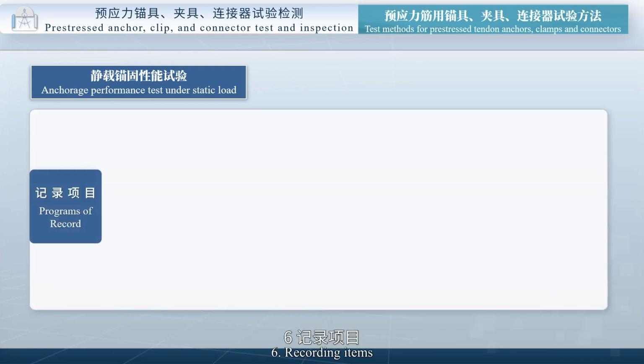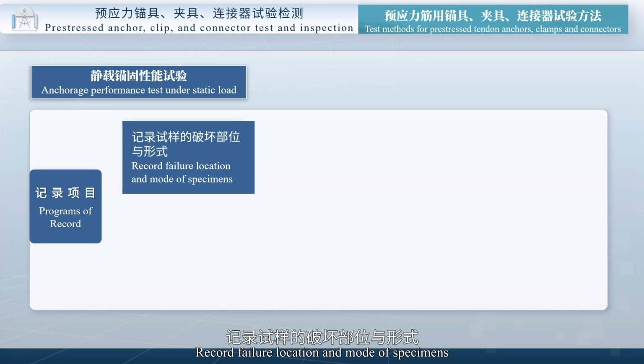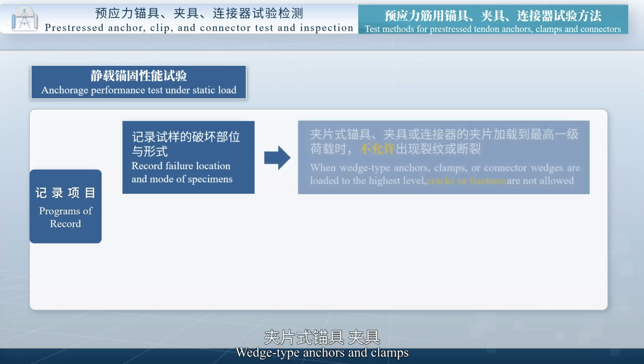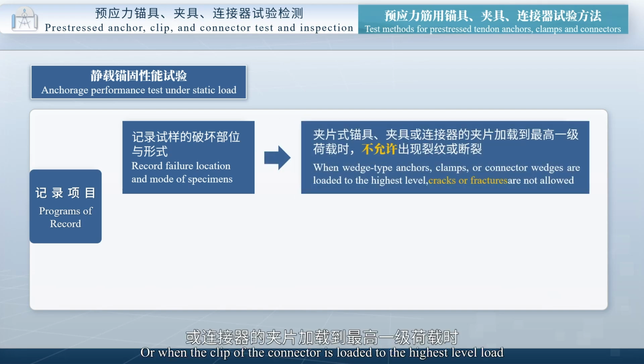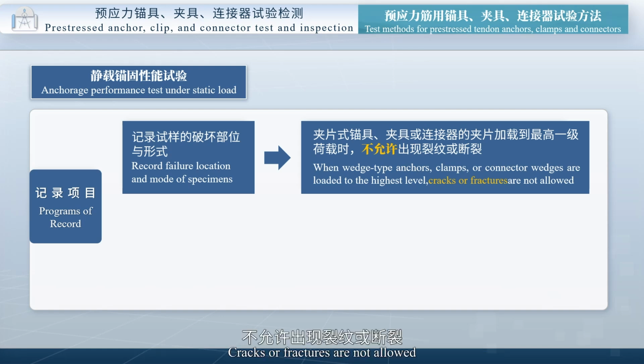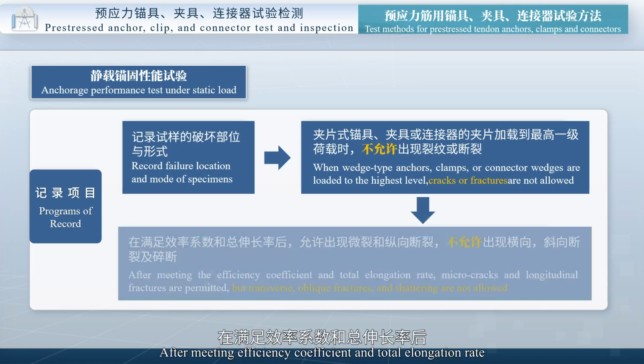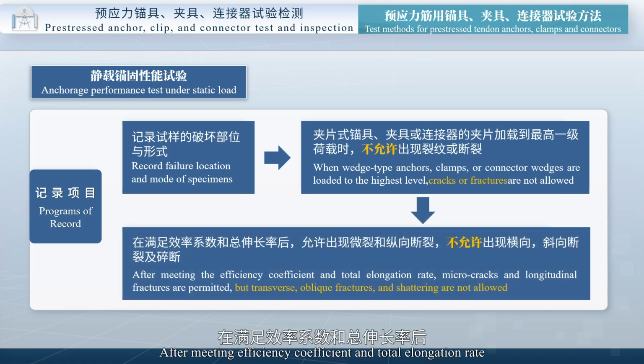Sixth, recording items. Record the failure location and mode of specimens. Failure location and mode of the assembly should conform to the requirements: for wedge-type anchors and clamps, or when the clamp of the connector is loaded to the highest level load, cracks or fractures are not allowed. After meeting the efficiency coefficient and total elongation rate, micro cracks and longitudinal fractures are allowed. Lateral deformation, diagonal fractures and fragmentation are not allowed.